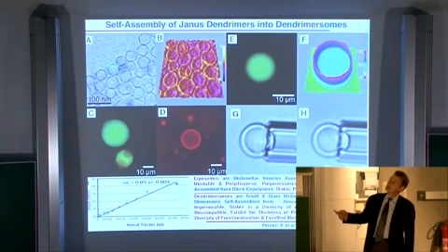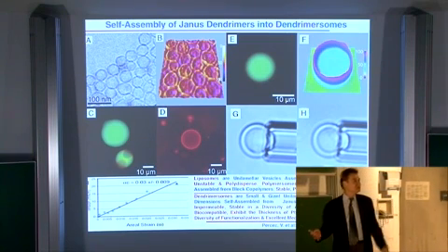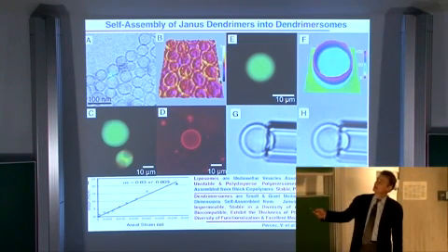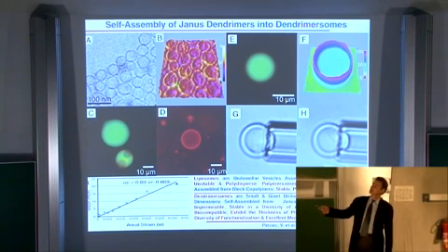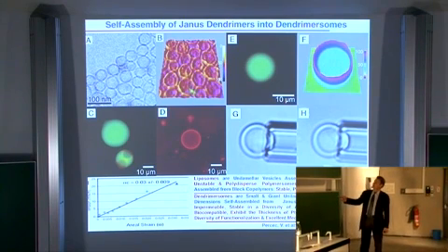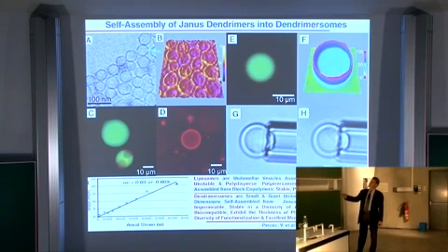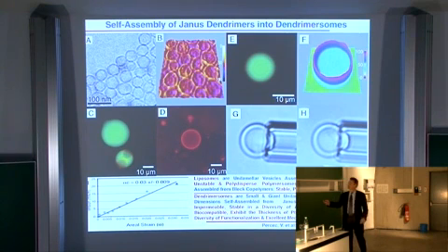So here is an example of cryo-electron microscopy. And you look at these molecules and you see that they have identical size, and that correlates very well with what you get from dynamic light scattering. You build a three-dimensional structure of these molecules and you see they have a hollow center where there is only water. And you can do experiments complementary to cryomicroscopy. Cryomicroscopy is done on very small vesicles. They are monodispersed, very stable in time.